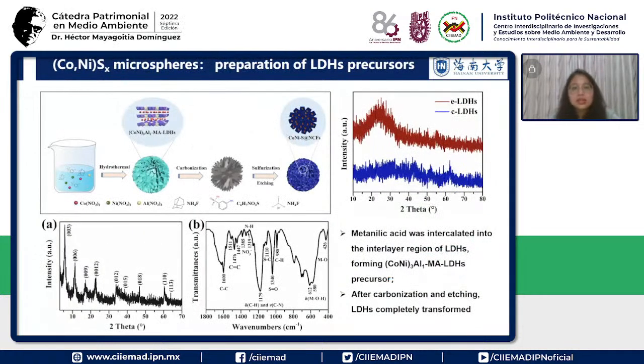And the next work is about the sulfide. The last one, before this, was the cobalt nickel selenide. But in this work we want to know what happens if we change the element to sulfur. So we followed a similar preparation, but the difference is we use this metanilic acid and put it into the interlayer of the LDHs, because we can see in this structure they have this material.